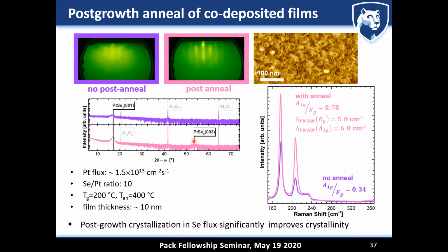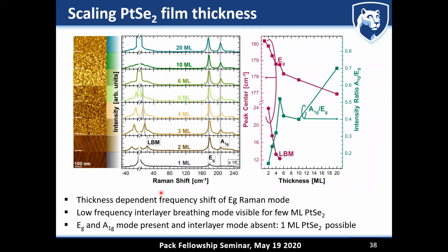And so we have a way to grow platinum diselenide, but we have to do it in a two-step approach, where we have co-deposition at low temperature first, and then a post-growth anneal under selenium flux second. When we apply this strategy, we can start scaling the platinum diselenide thickness all the way from 20 monolayers that we've done here, down to 1 or 2 monolayers. And we can see how nicely the E_g mode of the Raman shifts to higher frequencies as the film thickness gets lower. We also see this trend in thickness for the lateral breathing mode.